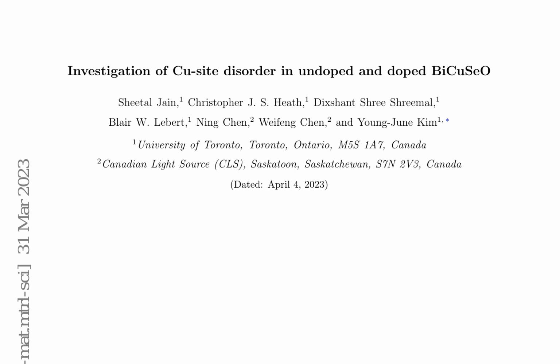For temperature-dependent studies, the highest doping concentration, x equals 0.08, of single-doped and dual-doped BiCuSeO samples, along with the undoped BiCuSeO sample, were selected. The energy of the incident X-ray beam was selected using a double crystal Si(111) monochromator, with higher harmonic contribution suppressed by a combination of Rh-coated mirrors and a 50% detuning of the wiggler.